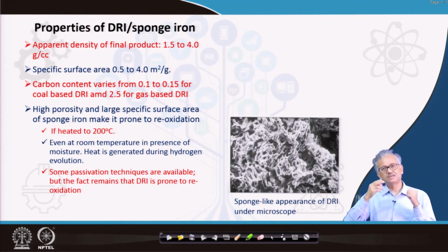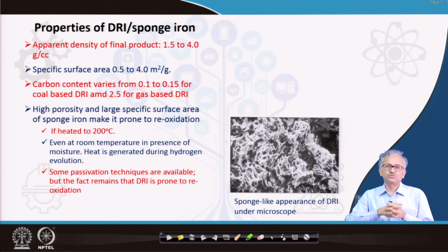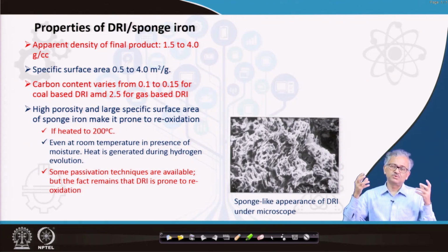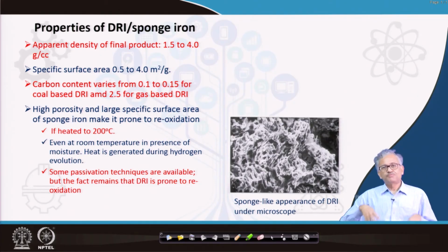I will talk about that, because coal-based sponge iron is protected by a slag layer to some extent. A slag layer is there that basically blocks the pores at the surface. So it is not that reactive and is less prone to reoxidation, but the gas-based DRI is very much prone to reoxidation.